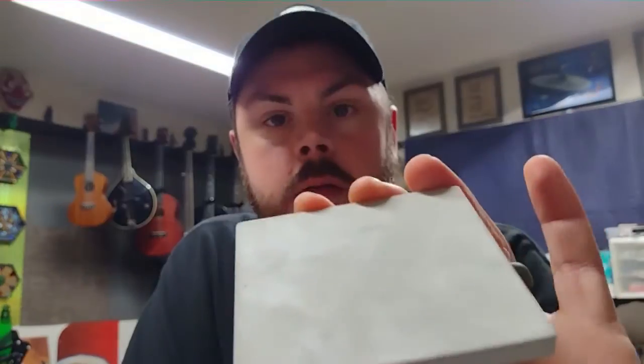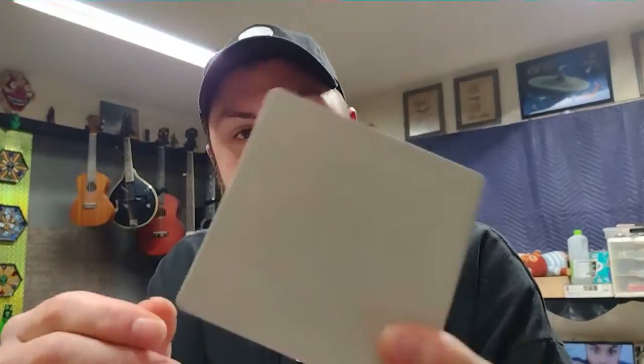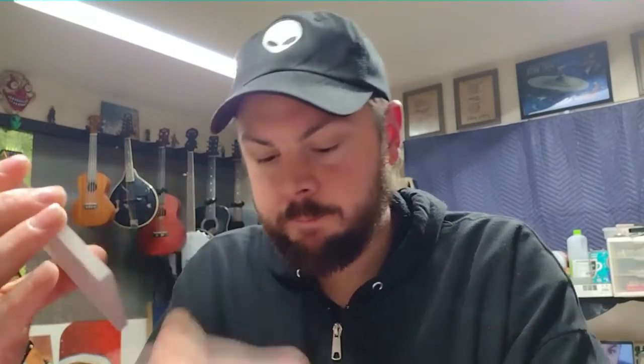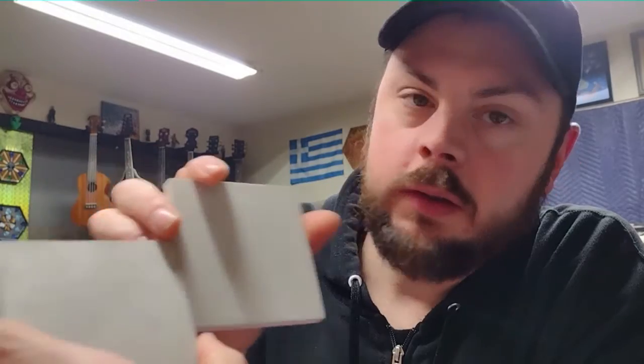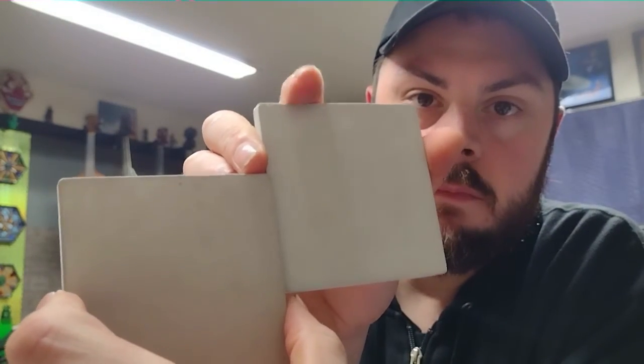Now, for the other two, so here's the 50-50 mix. Nice finish. I like it. Nice and smooth. 75-25, same thing. Really not much difference. You can barely tell that the higher ratio of Pure Cure is lighter in color, which is to be expected because it's white and the cement mix is dark gray. But still, both of them have the characteristic kind of ceramic-y feel and sound to them.